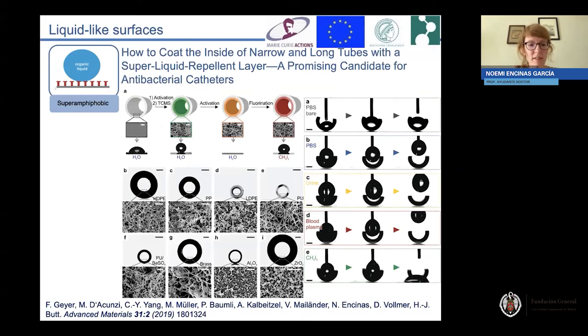So we used this to coat narrow and long tubes so we could define a promising candidate for catheters that couldn't undergo bacterial adhesion, therefore being able to minimize infections. So this work was published in Advanced Materials, and here what we did was to activate long tubes of different materials, ranging from polymers such as high-density polyethylene, polypropylene, low-density polyethylene, or polyurethane, up to composites, metals, and even ceramics.